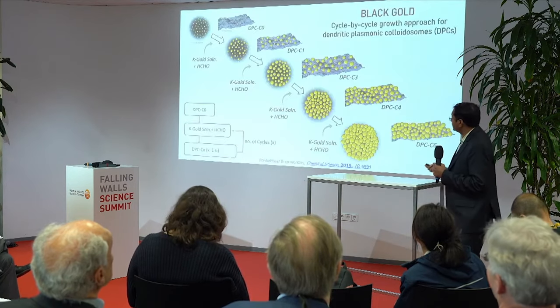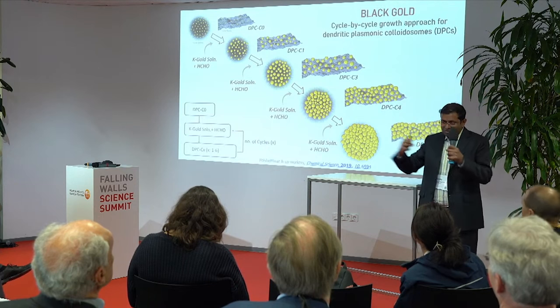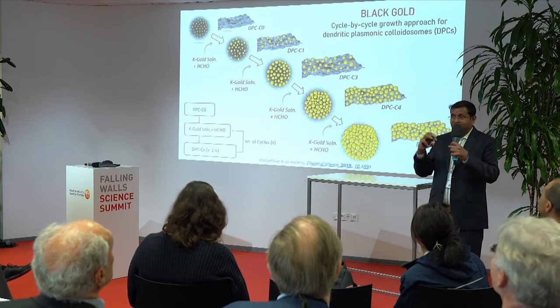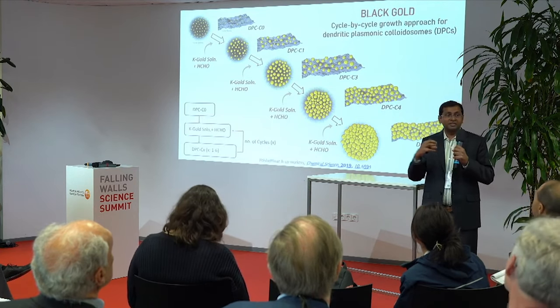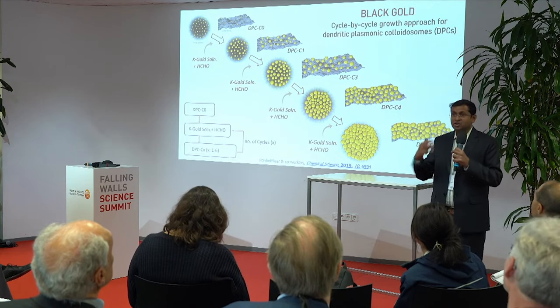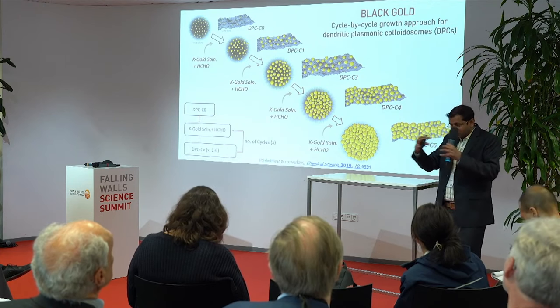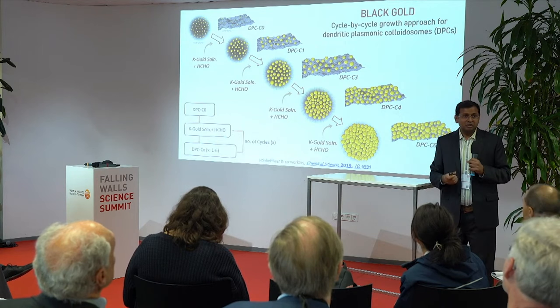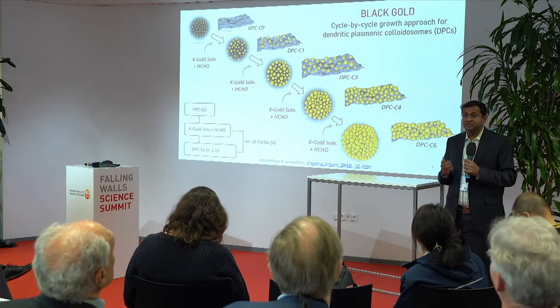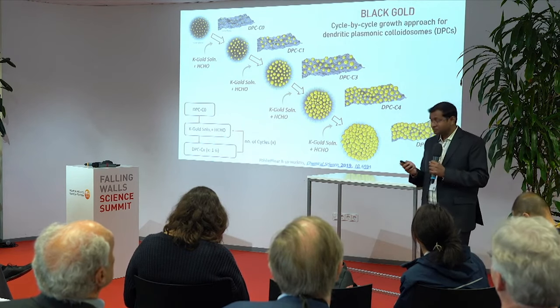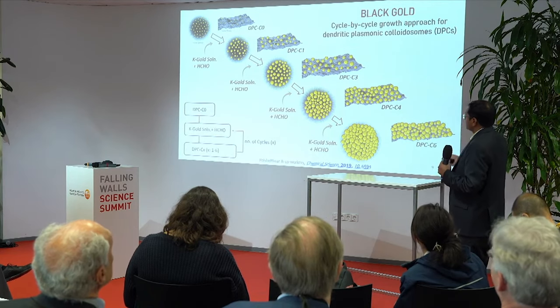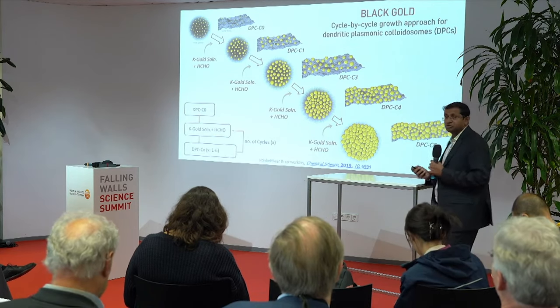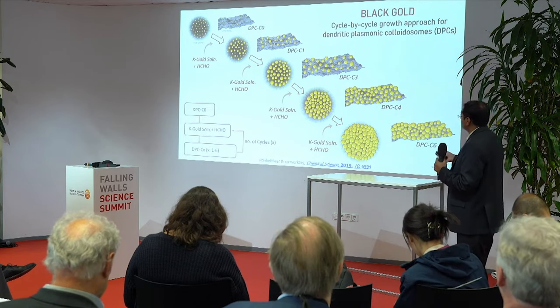So what we did then, we came up with the idea that you bring lots of these gold particles closer, and then the electron clouds of the gold particles start coupling with each other, called plasmonic coupling. They start talking with each other, and they together then resonate with different wavelengths of the light, and ideally you should get a broadband light absorber. So this is a typical synthesis protocol, simply tuning the nucleation and growth process. We were able to tune the distances between these nanoparticles.